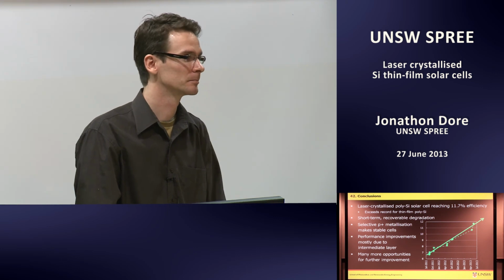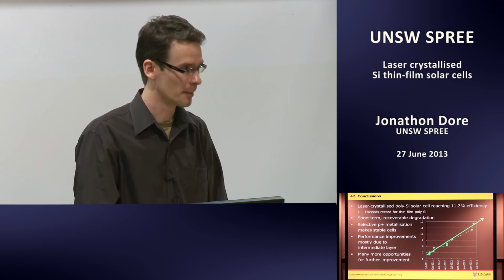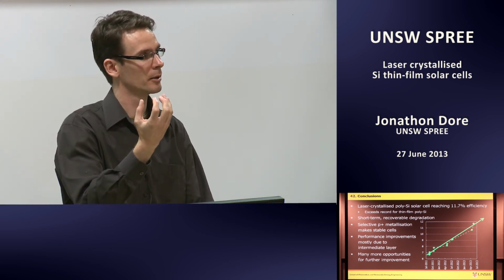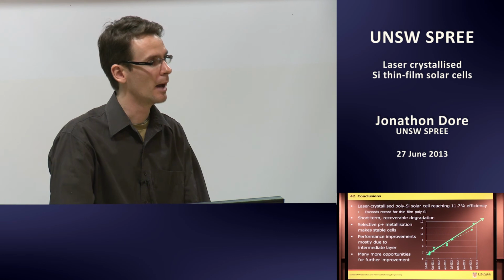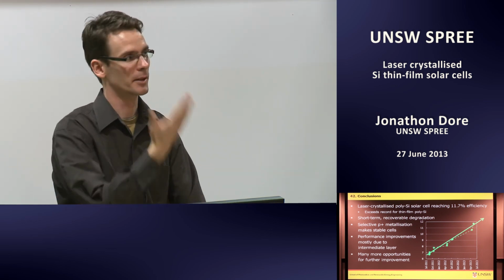One more, following on from this: that resist seems to be very important to be able to place that bottom contact all the way through without shunting your emitter. How is that done? How can you open the bottom only and deposit the metal? It's done by firstly inkjet opening of the resist layer, and then etching through the silicon using a wet chemical etch process. Finally we do a reflow process. By exposing that resist layer to solvent, we can flow the resist back over those walls and cover the emitter. That's simply the old CSG process.